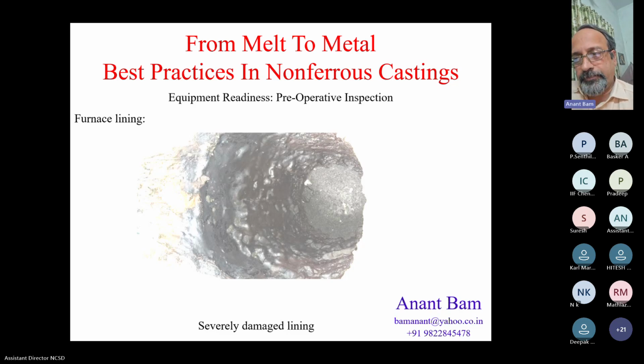This is a photograph of a cast iron induction furnace with a very dirty condition of lining. The lining is worn out in multiple locations. There is a lot of slag adhering to the faults or the cracks or the worn out part of the lining. And such lining is totally unreliable, and it is an invitation to major accidents. Unfortunately, I could not get a photograph of aluminum melting induction furnace lining because there are very few induction furnaces in aluminum melting. Next slide, please.